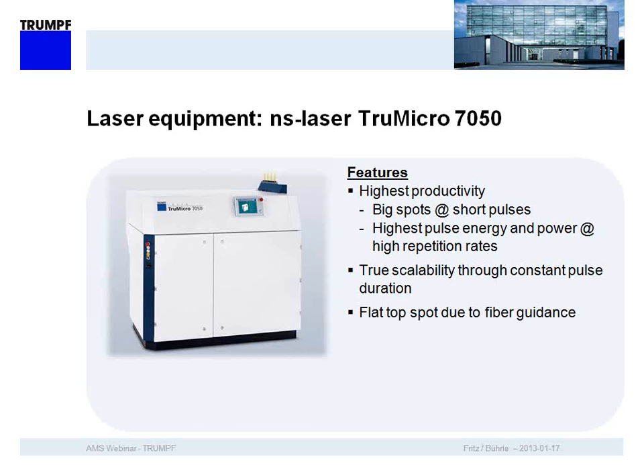optical arrangements. And very interesting of that laser is it has a very high pulse energy power with a high repetition rate, very stable in the pulse, which helps, of course, in that removal of the part of this very thin layers. And we can go to very high frequencies, which we'll explain now. So very important in this kind of applications.